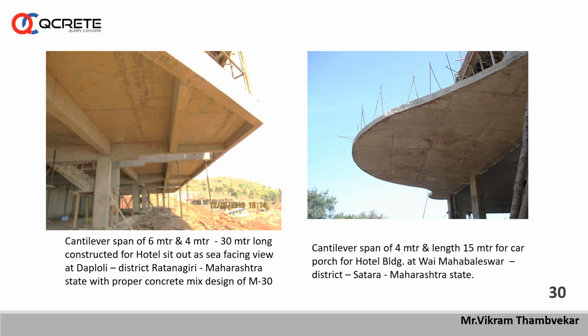So while making fresh concrete, all these necessary precautions must be taken. I'll tell you, here at our Dapoli project, we didn't get better quality of coarse aggregate, and even river sand is also not good quality. It contained a large amount of silt, as well as some flaky material. The 10 mm down aggregates and 20 mm aggregates were also flaky.